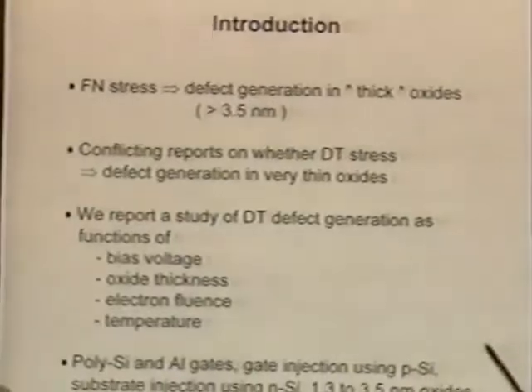I say it does. Some people have put some papers out in 94 and 95 saying that they don't see that, but it's because it's a subtle effect. I believe, in fact, the defect generation that I see is sort of the principal degradation mechanism in oxides that are less than 35 angstroms, and we'll talk about that. That's the focus of my talk. And I hope, if nothing else, I've convinced you of the bad news that, yes, you still have to be worried about defects in direct tunnel oxides.